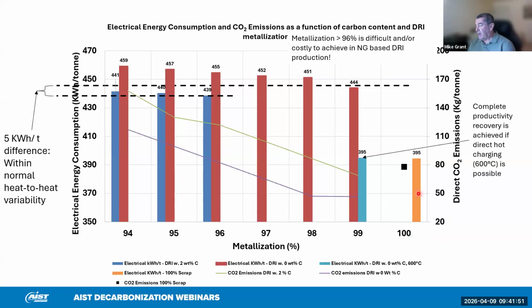If you are able to hot charge your DRI, we can go to 600 degrees C. We can bring that electrical power consumption down to the equivalent to that we had for the reference case with scrap, and this will recover all of the productivity lost through the use of DRI in the system. So in reality, the zero carbon DRI with high metallization is effectively as good as 96% metallized DRI with 2% carbon.